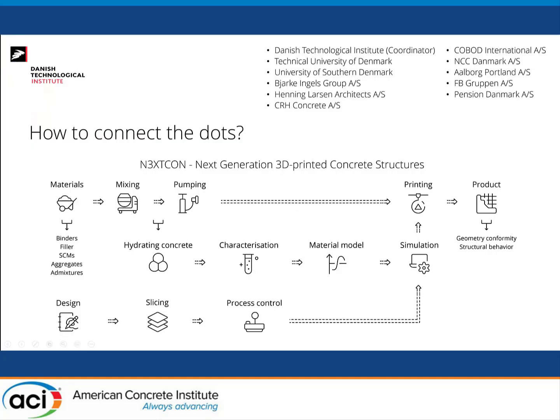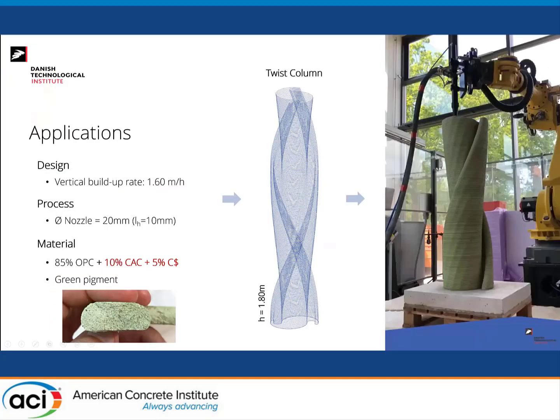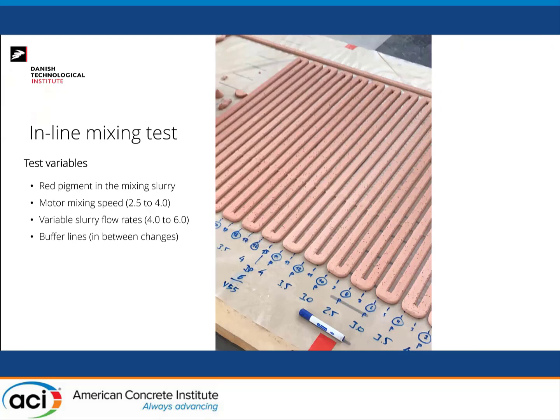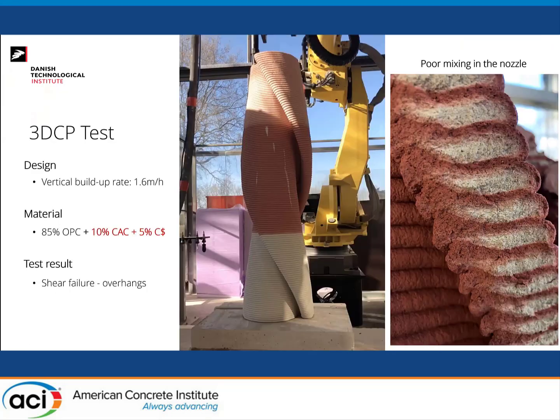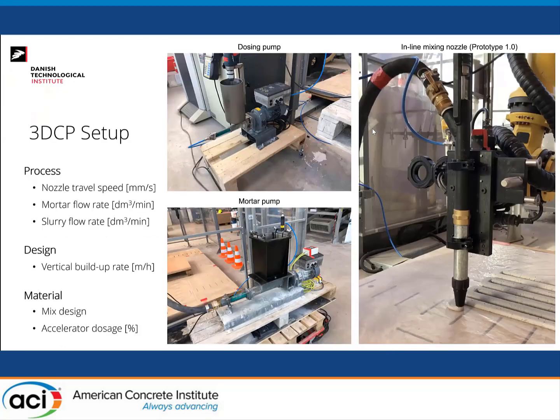Why was the calcium aluminate cement injected in the nozzle, and why were both retarders and the calcium aluminate cement used at the same time? It was activated in the nozzle as a slurry. As you saw back in this slide, there is a compartment where we mix the slurry, and then the slurry is pumped into the nozzle. So the slurry comes in here, and then it's injected at this point. So it is a slurry.